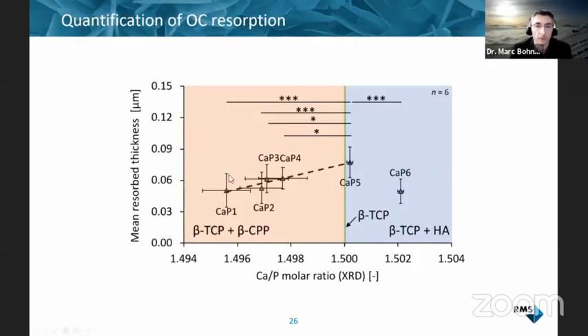And if we look in more detail at the data, we did a statistical analysis. There's a strong effect of the calcium to phosphate ratio below 1.5, which was actually, when thinking about it, not so surprising. So we had an inhibition of the resorption by having a bit more calcium pyrophosphate, which is a strong inhibitor of osteoclasts. What was more surprising was the fact that we had a 30% drop with not even 1% beta-calcium pyrophosphate. So you could imagine that with 3 or 3.5%, you would completely inhibit osteoclast